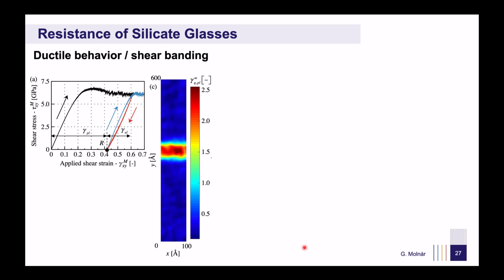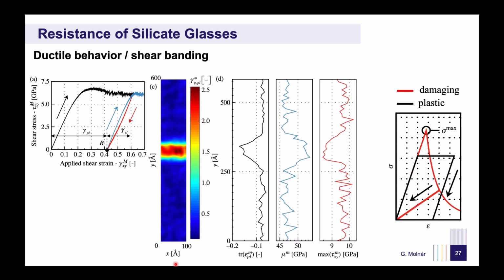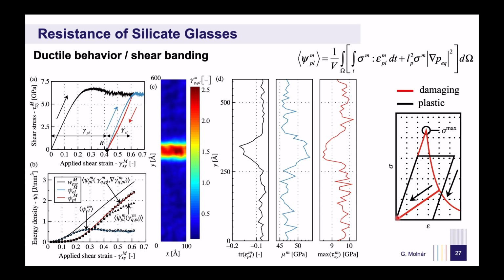When we increased the sample size along one direction, we observed the formation of shear bands due to the localized softening. For a long time, shear bands were believed to form due to local damage, a reduction in shear strength. However, by measuring local material parameters such as densification, rigidity, and yield strength, we found that shear bands actually increase in density, which in turn increases local rigidity. This contradicts traditional damage mechanics, which would predict a reduction in stiffness. Instead, the true cause of shear bands is not damage, but the phase transition that weakens the yield strength. By introducing a gradient term to describe plastic strain, similar to phase field models, we were able to recalculate global energy variations and define a third length scale for glass deformation.